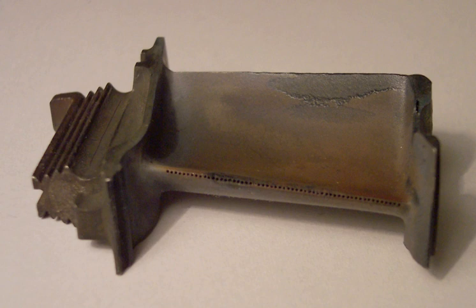For the aluminide bond coatings, the final composition and structure of the coating depends on the composition of the substrate. Aluminides also lack ductility below 750 degrees Celsius, and exhibit limited thermomechanical fatigue strength. The Pt aluminides are very similar to the aluminide bond coats except for a layer of Pt, 5 to 10 micrometers, deposited on the blade. The Pt is believed to aid in oxide adhesion and contribute to hot corrosion resistance. The cost of Pt plating is justified by the increased blade lifespan.